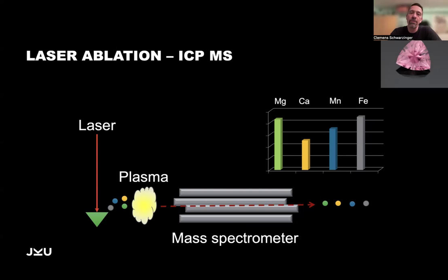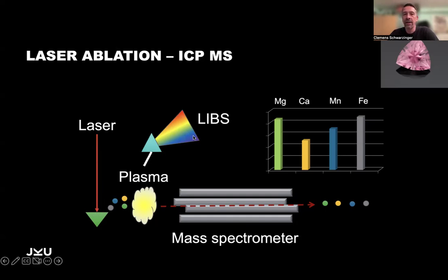XRF is something a little bit cheaper, but has its limitations. For example, the instruments that are used for determining the metal content in gold alloys will not work for the same purpose like the garnet analysis. A technique that also starts with the laser ablation, but is a little bit cheaper than the ICP-MS, is so-called LIBS, laser-induced breakdown spectroscopy. In this case, we have the same first step. We have the laser, and the laser creates the plasma here, and from this plasma, we just collect the diffracted light. And depending on the wavelengths of the light, we can assign them again to our elements, and we can assign the elements in this formula of the garnet.